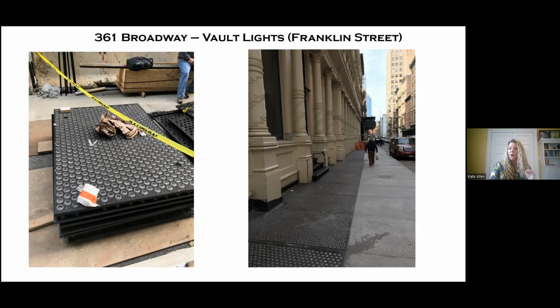We always pour these panels in ductile iron. We've actually redesigned and re-engineered these panels to be more efficient, down to the types of grout we use and the tapering of the hole to receive the glass. We have a source that we use for all of our glass in upstate New York. It's fantastic, but we definitely pour these in ductile iron because of that flexibility. The standard sizes we typically see are about 3 by 4, or 3 by 3'4". They weigh about 200 pounds, and we pour them anywhere between 1 inch to 1.25 inches thick. We've spent a lot of time developing these and our ability to design and install them.